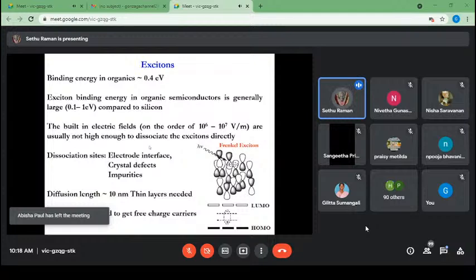The exciton binding energy in organics is about 0.4 electron volt. Exciton binding energy in organic semiconductors is generally large compared to that of silicon. The built-in electric fields are usually not high enough to dissociate excitons directly. So in organic solar cells, where is the exciton dissociated? The dissociation sites in organic semiconductors are the electrode interface, crystal defects and impurities. The diffusion length is about 10 nanometer, so a thin layer is needed for the diffusion process, so that it can be dissociated to get a free charge carrier.